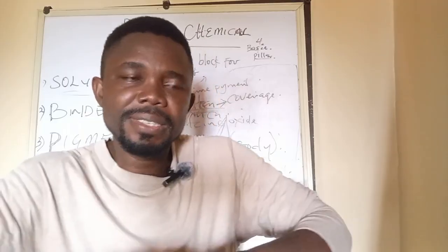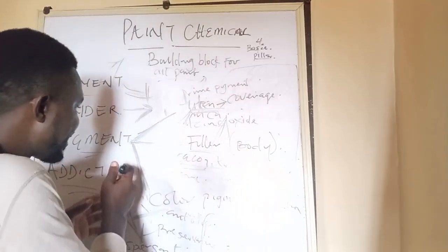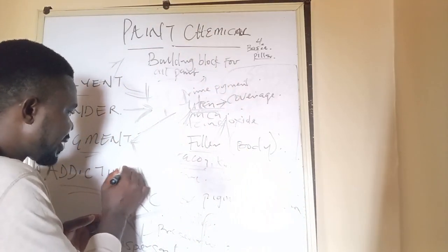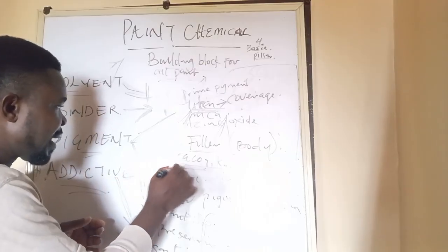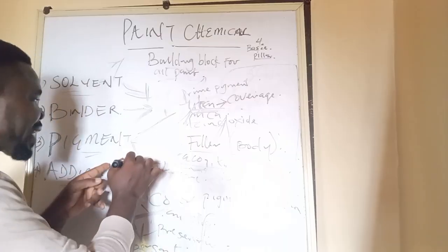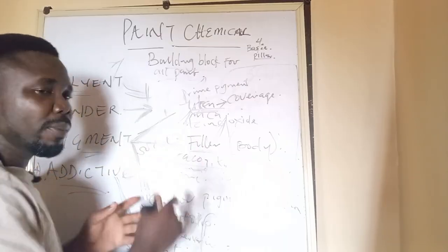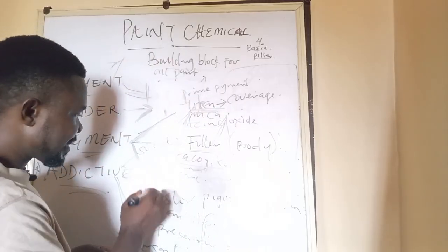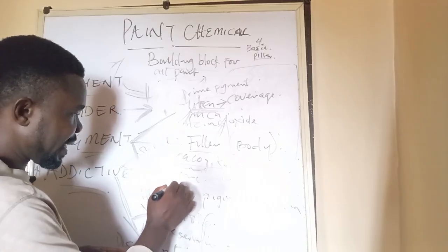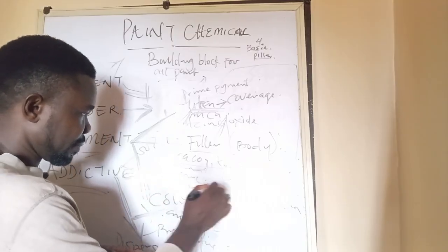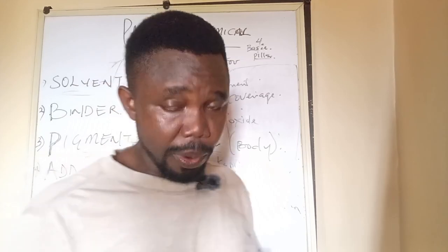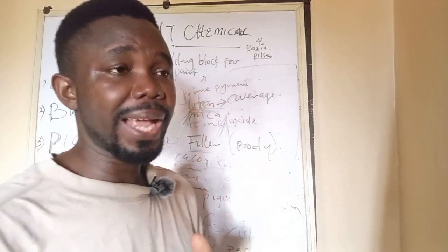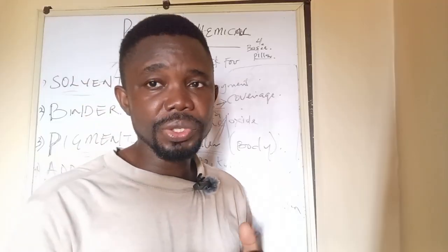For example, when propylene glycol is added, which can serve as a co-solvent and as a trace-amount additive, it solves the problem of roller marks. If the additive ethylene glycol is added, it serves the purpose of anti-thaw and antifreeze.